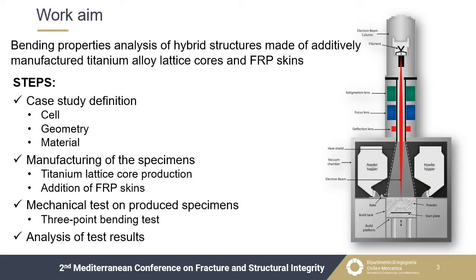Then, the specimens were produced according to a two-step process. In the first one, the cores were manufactured through the EBM process, that is the electron beam melting, an additive powder bed additive manufacturing process. Then, the skins were added by co-curing the prepreg layers on the cores. After, the produced specimens were tested and the obtained results were presented and discussed.